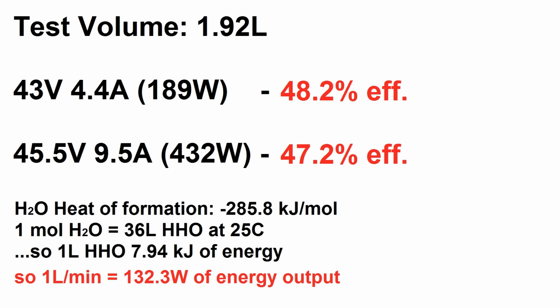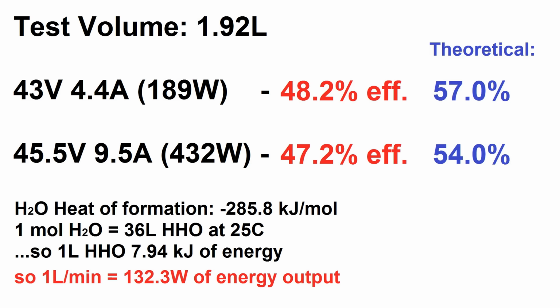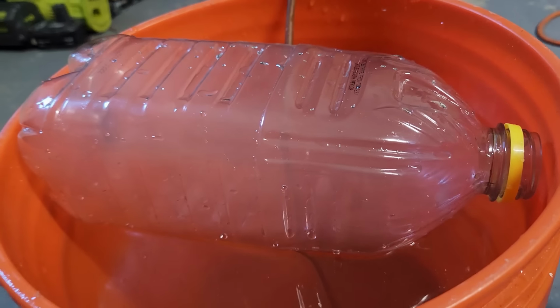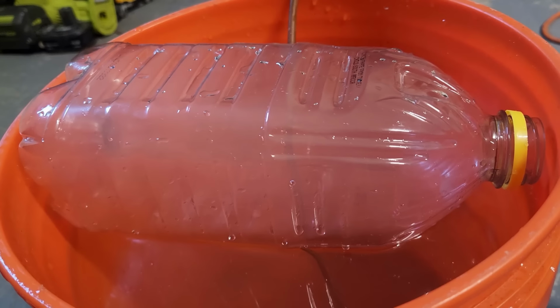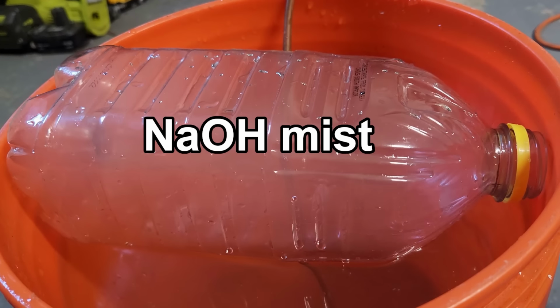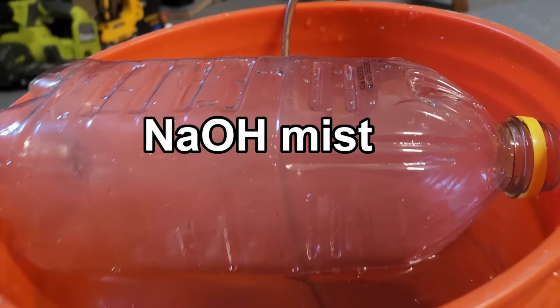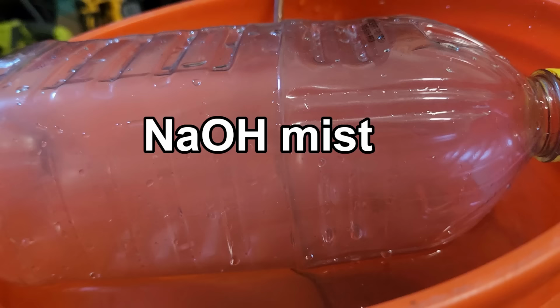This is actually pretty good because theoretical efficiency is 57% and 54% respectively, and we're not too far off from those numbers, so we're getting almost all the gas we possibly can given the input power. Just an interesting side note, when the bottle is completely full, you can see it's somewhat opaque, and this is just a mist of superfine sodium hydroxide particles. The sodium residue is the reason the torch flame will come out bright orange. If it's totally pure, the flame is actually invisible.